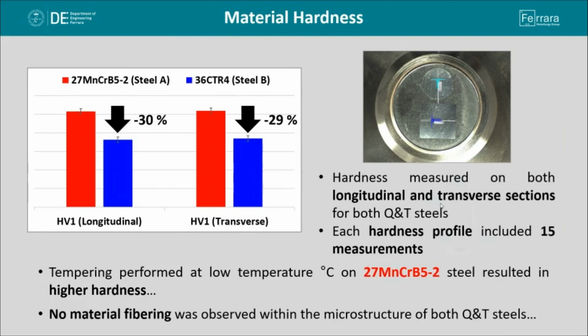from broken tensile specimens. And we can see here in the present slide that although steel A exhibits higher hardness with respect to steel B, hardness values are almost the same if we take into account longitudinal and transverse sections of this metallographic sample. So we can assess there's no material fibering and so no wrong fibering processes affected the investigated components from which tensile specimens were extracted.